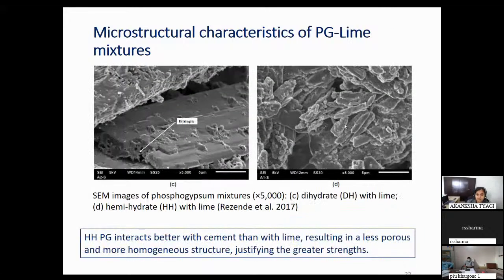Okay. And a similar thing was seen when this phosphogypsum was added to lime. In this case also, a similar thing happened, like ettringite formed. But the thing is, ettringite forms a kind of network at first, and this increases the strength. But after a certain period of time, if this ettringite formation is too much, if there is an excess of ettringite, then there is a reduction of strength. So the same thing happened with the dihydrate phosphogypsum with lime. And here, this is the hemihydrate phosphogypsum with lime.